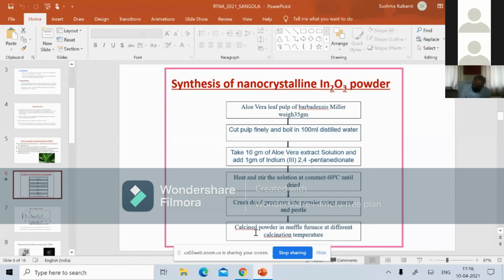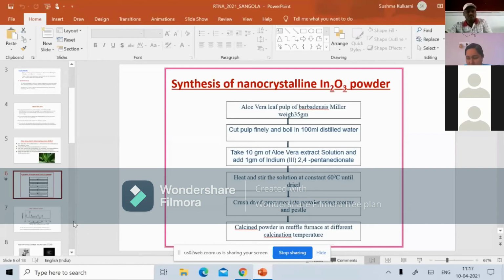Here in this experiment, I have chosen a temperature of 450 degrees Celsius. And now that brownish color is turned into yellowish colored powder. Now I can confirm that the powder is formed by using the XRD spectra. That XRD spectra has been taken from 20 degree angle. Here, these reflections that I got are indexed into JCPDS card number 060416, and I used the Debye Scherrer formula.